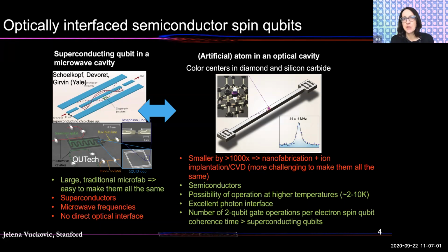We still have to cool down the chip, but temperatures of a few Kelvin work just fine, which means you can do experiments in simpler closed cycle cryostats instead of dilution refrigerators. We already have excellent optical interfaces for these structures, as opposed to superconducting qubits, where you basically have microwave interfaces, and in order to network them, you have to build quantum transducers that people are still developing. But we have an excellent optical interface for granted. And maybe most interestingly, for scaling of these platforms, the number of 2-qubit gate operations that you can perform per electron spin coherence time is greater in these systems than for superconducting qubits.